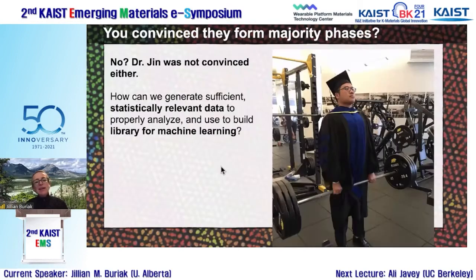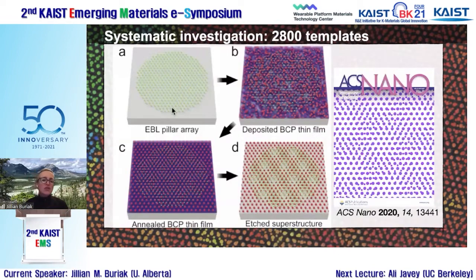Okay, now, I didn't convince you at all that you're getting anything other than a mess. And I don't think Chongjin was convinced either. So what we wanted to do, because we do a lot of machine learning with sparse data using experimental results, was generate statistically relevant data to have any sort of sense of being able to do prediction. And so what he did was to actually use electron beam lithography to draw in the first silica dot